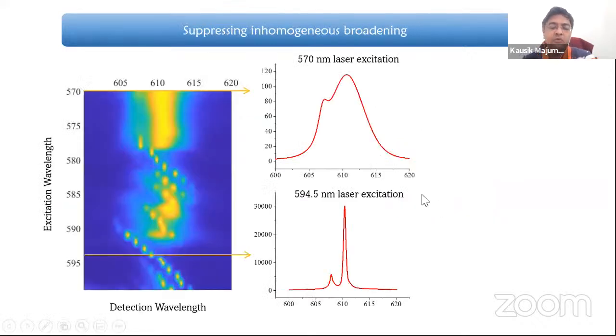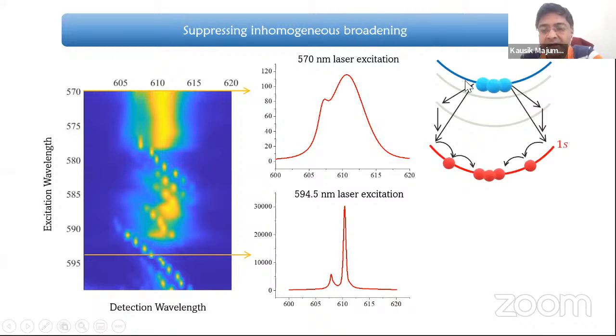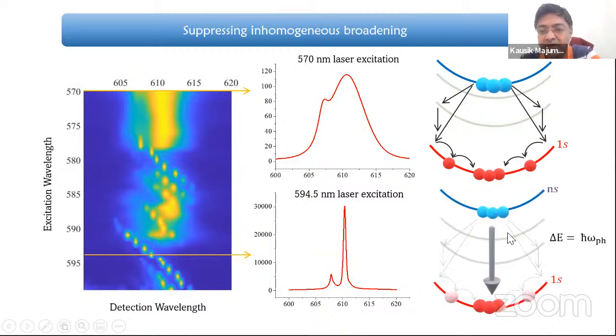What we did is that we had a tunable excitation, and we were measuring the detection in a spectrometer. As we change the excitation wavelength, from a broad line width it suddenly comes down to a narrow one. This is normalized, so it's not very obvious here, but about 120 in intensity here and 30,000 here, so there's about 300 times enhancement in the intensity, plus it became very narrow. Usually we relax through multi-phonon states, while in this case it resonates with the A1G phonon, and in a single shot comes down here, giving very high luminescence and a very narrow line width.